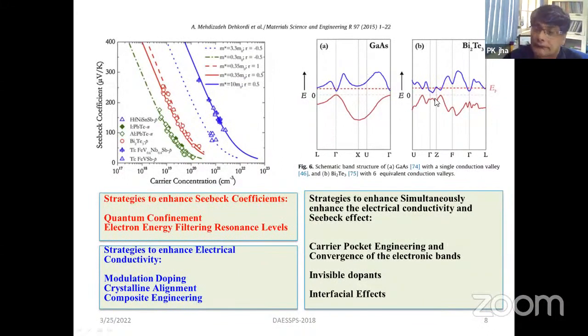And this is another aspect of the electronic band structure, that Bi2Te3 is one of the best materials for the highest figure of merit, or in fact you can say one of the best thermoelectric materials. And these are basically the valleys. So in this case, if you count, there are 6 valleys in the conduction band, and it is found that if there are 4 to 6 valleys in the conduction band, those types of materials are good for better thermoelectricity. And on this side, you can see gallium arsenide, which has only 1 conduction valley, and that is why it is not good.